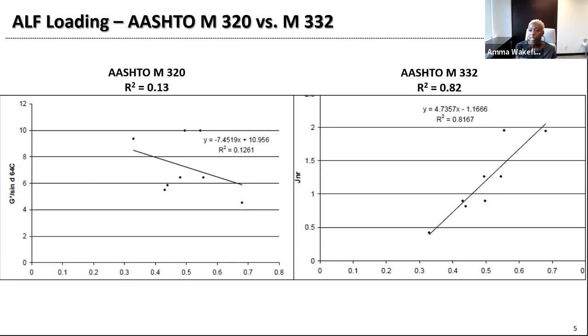Now, what you're seeing in the graphs is a correlation between each of those parameters compared to a field assessment. And it's an accelerated field assessment that was done at the Federal Highway Administration's Accelerated Loading Facility, or ALF. What the ALF does is it simulates truck traffic with controlled loading and pavement temperatures. And because of this, within a few months of running at this facility, you can simulate years of traffic, and you're able to collect data related to the distresses, and then you're able to compare the different pavement sections. So that's what was done here. And in the left graph, it shows the correlation between the G* over sine delta rutting parameter in the AASHTO M320 and how it compared to the measurements from the ALF.